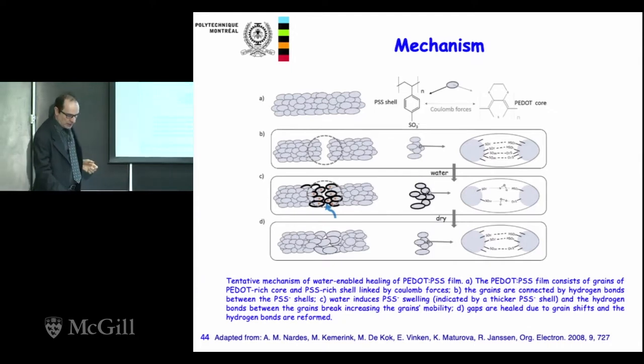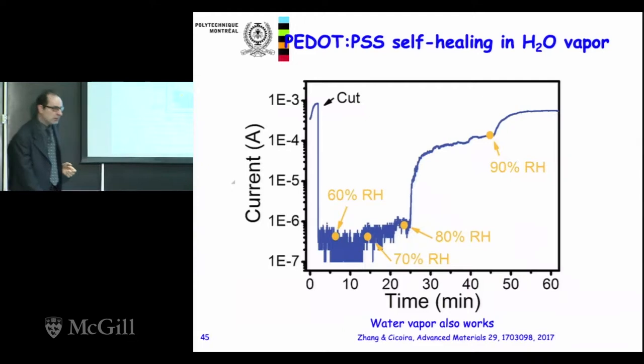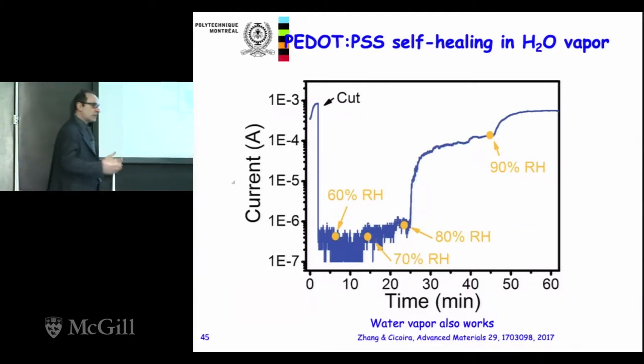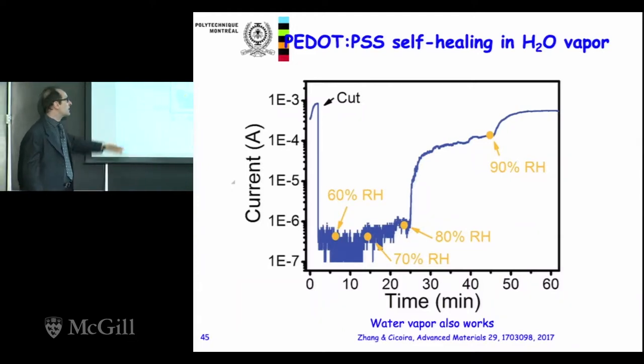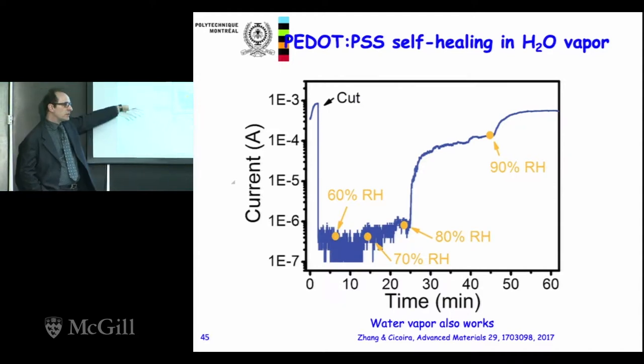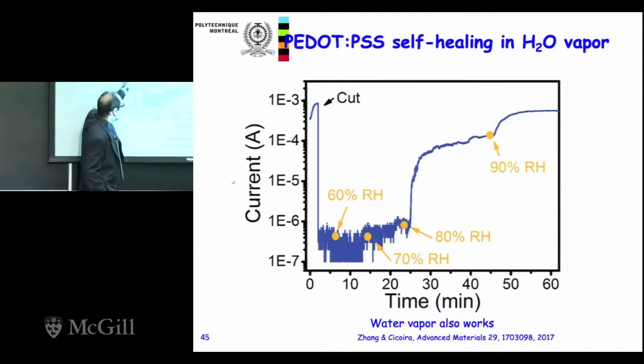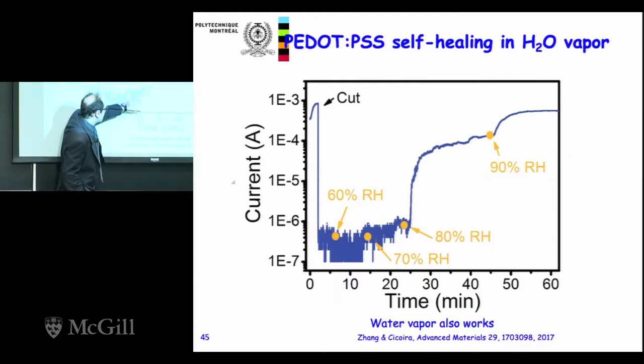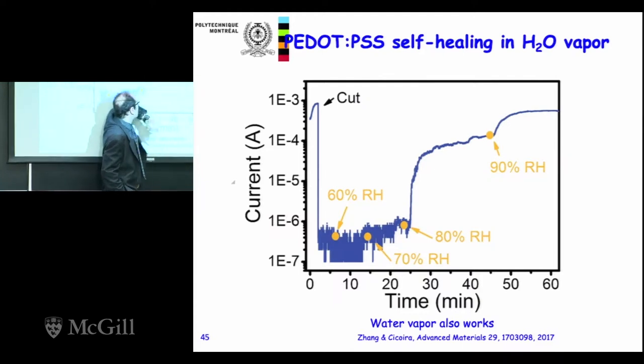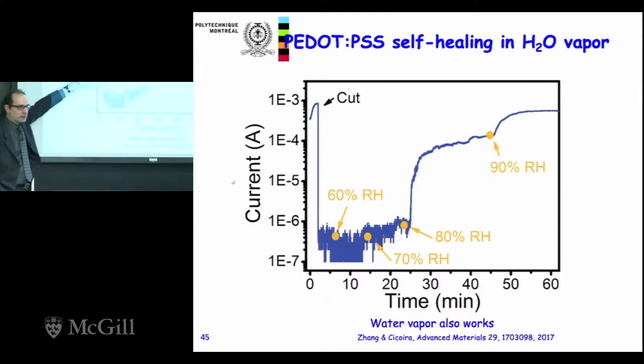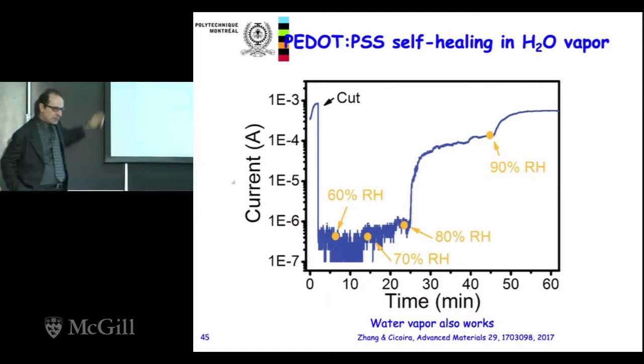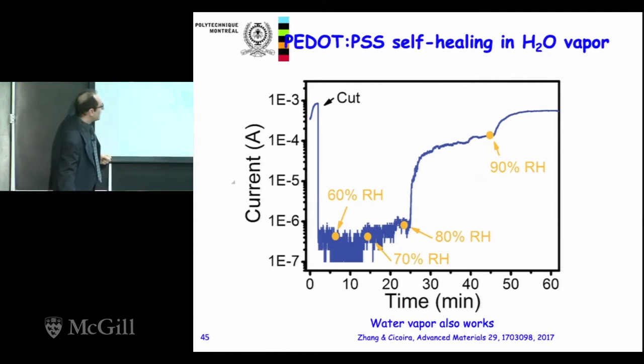Then another idea we had is let's try this material in humidity conditions. Let's see what happens. So this is the same measurement carried out in a humidity chamber. We cut in the humidity chamber, and then we changed the humidity. We don't observe much up to 80%. Then we start to see the current increasing. And if we increase to about 90%, we have almost a total recovery of the current. So this means the materials can be healed also by the vapor.